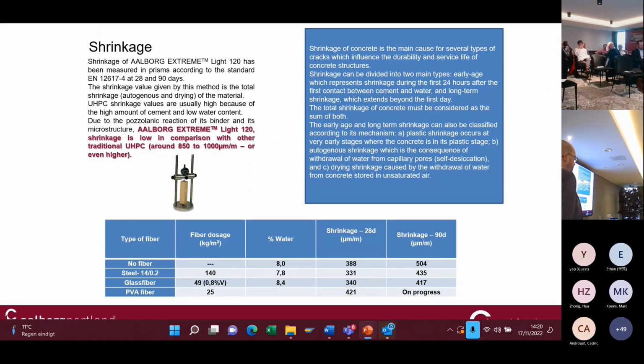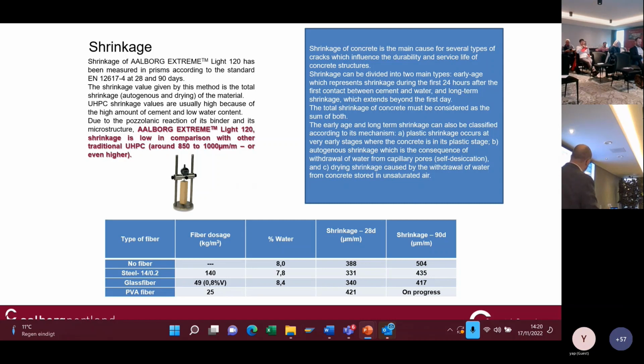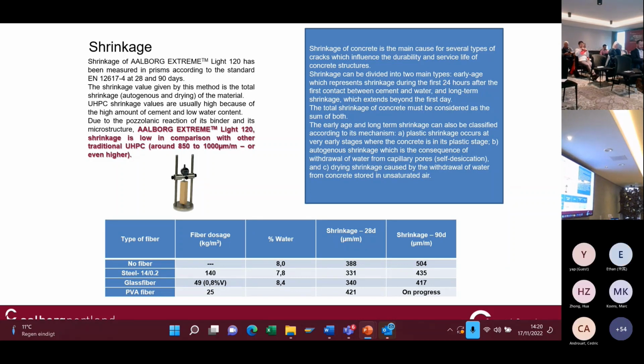So the main benefits of these products that are based on the FutureSense technology with inclusion of metakaolin is firstly the shrinkage. Shrinkage in UHPC, it has a lot of fine fractions. It's really a topic that you have to consider. And we have seen with working with metakaolin as fine addition that we can limit the shrinkage at 28 days at around 420 microns per meter, while at 90 days, okay, it's a little higher. But if you compare it to other UHPC mix designs with silica fume, it's a lot lower.